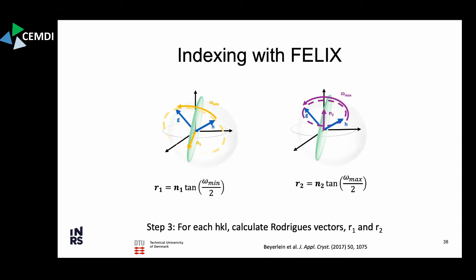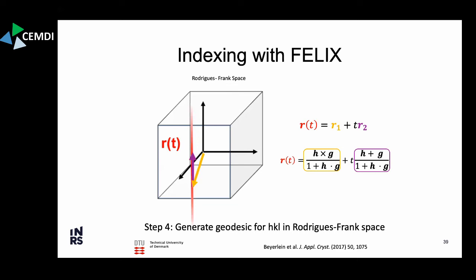So this angle that you have to rotate can define this axis of rotation, and then you have the minimum angle necessary, and then you also correspondingly have the maximum angle necessary. And this is about the vector which is directly in between the G and H vector. Whenever you have two vectors on a unit sphere, the smallest angular rotation to bring one onto the next is about the normal to the plane defined by those two vectors, and the longest is about a vector that is in the plane defined by G and H. Does that make sense? Sorry, I'm just making sure I haven't lost you completely.